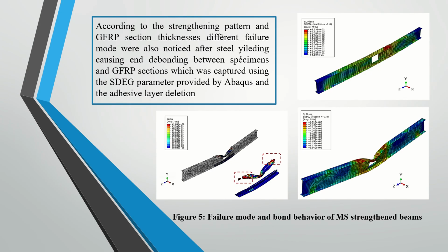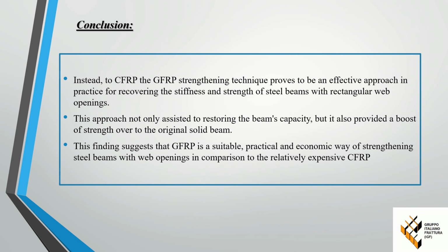According to the strengthening pattern and GFRP section thicknesses, different failure modes were also noticed after steel yielding, causing debonding between specimens and GFRP sections. Compared to CFRP, the GFRP strengthening technique proves to be an effective approach in practice for recovering the stiffness and the strength of steel beams with rectangular web openings.